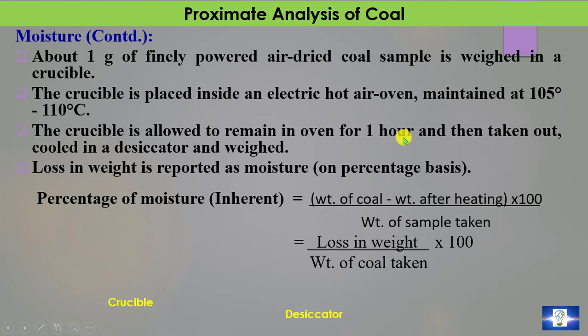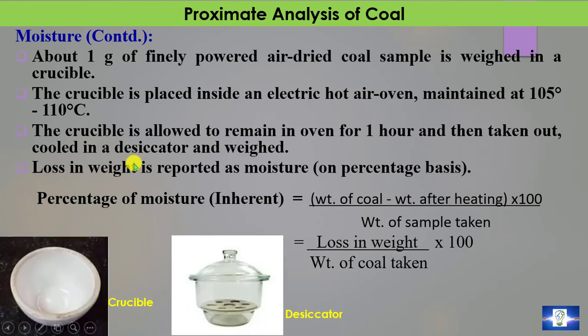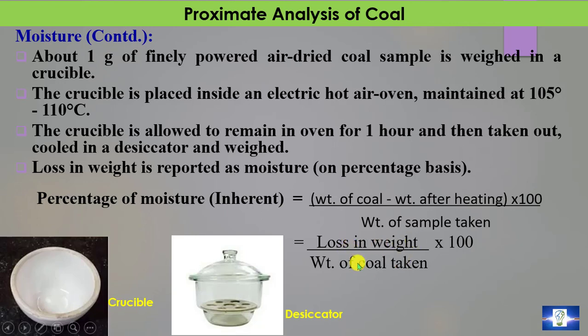The crucible is then taken out, cooled in a desiccator, and weighed. The loss in weight is reported as moisture. One thing to remember: this moisture is only inherent moisture. The percentage of moisture equals the weight of coal taken minus weight after heating, divided by weight of sample taken (1 gram), multiplied by 100 — that is, loss in weight divided by weight of coal sample, times 100.